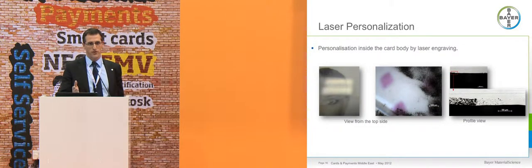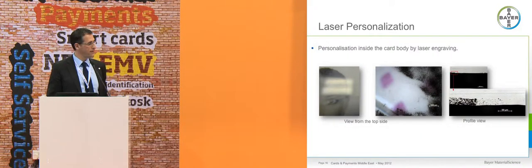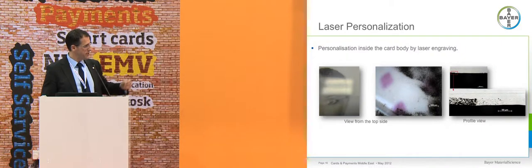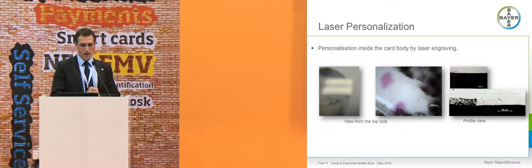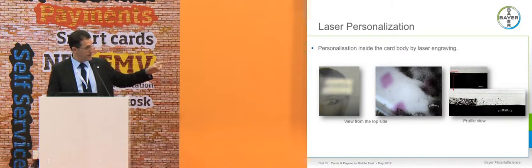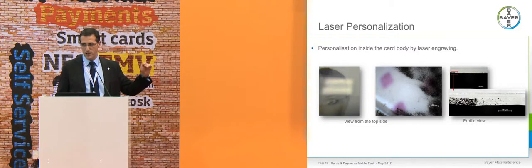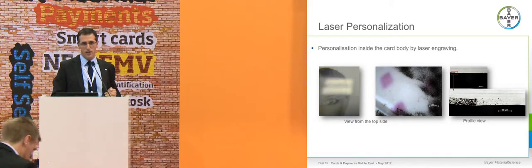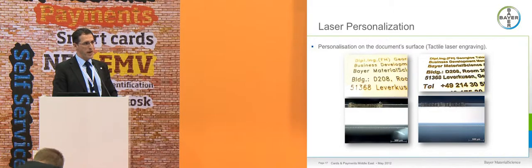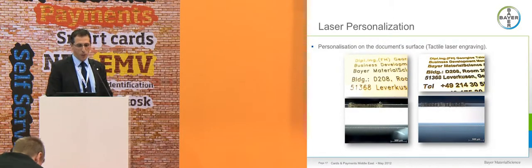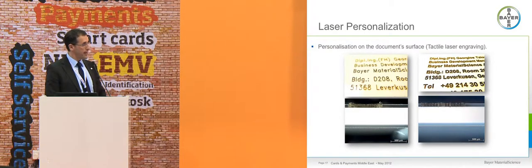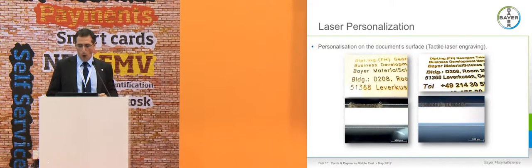Personalization, you can do it in two ways. Having a glossy surface after the laser personalization operation. You see it here. The picture of that lady looks very glossy, so the image is created fully inside the document. You see the cut through the profile of the card there, covered by transparent film. But you can do it also in another way. You can make a so-called tactile laser engraving by adjusting the laser beam of the laser engraving machine, but also in a certain way by the construction of the document.